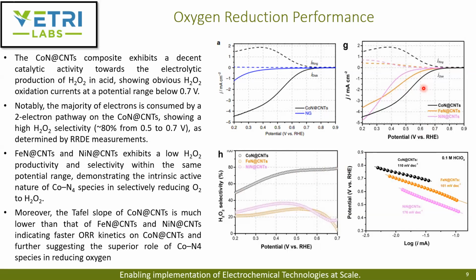And on this LSV over here, we can see how it compared with the iron and nickel doped carbon nanotubes. And one thing we can notice here is, as expected before, cobalt had a higher peroxide selectivity, and it reduced oxygen through this two electron transfer pathway, because you had less than 40% for both the iron and nickel doped, and 80%, like twice the selectivity, for this cobalt doped. And moreover, the Tafel slope is also lower for the cobalt doped compared to the iron and nickel doped, indicating that the cobalt doped has faster ORR kinetics, and it further suggests the superior role of this CoN4 species in reducing oxygen through this two electron transfer pathway.